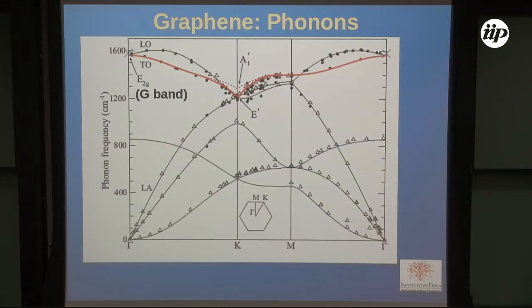Here is our calculation, and you see that, for instance, here in this dotted point are the DFT calculation, and this orange line is the GW calculation. So close to the K point, due to some aspect that I won't be able to talk a lot about, there is a big difference between the two calculations. So here we need to take care, so we have GW corrections close to the K point to have a good description of the phonons also.